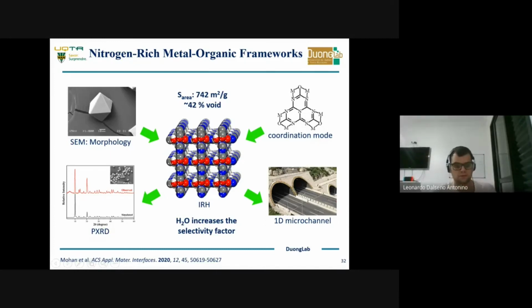First of all, you take this ligand here, you coordinate it with metals, and then you get some crystals. You take one crystal, do single-crystal X-ray diffraction, and solve the structure. What we found is that the wall of these materials contains a lot of nitrogen, which is what we want when we think about van der Waals interactions with the gas.